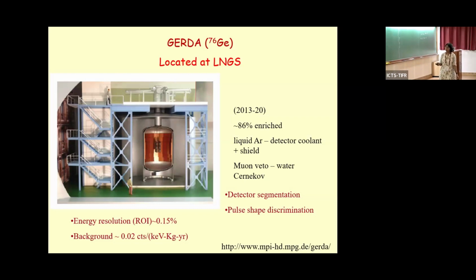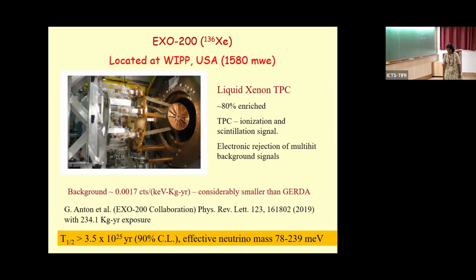The energy resolution, as expected, was very high, 0.15%. The expected background index was 0.02 counts per keV per kg per year in the region of interest. And I think they didn't quite get that, but still, this was fairly good. This one ran from 2013 to 20, and they have put a limit, and GERDA is no longer running. Moving on to the 136 xenon.